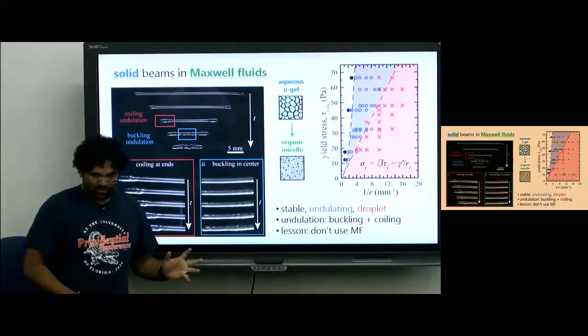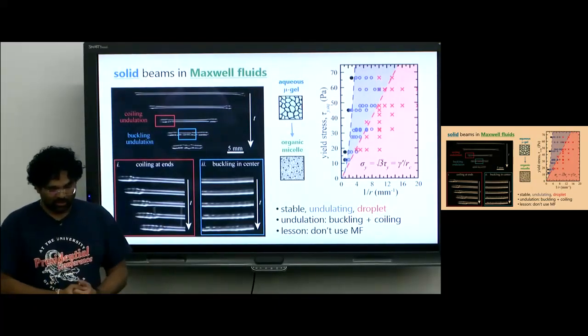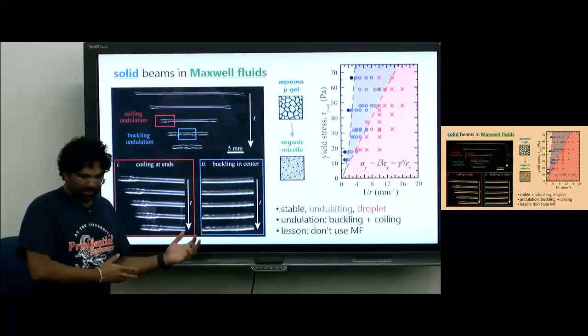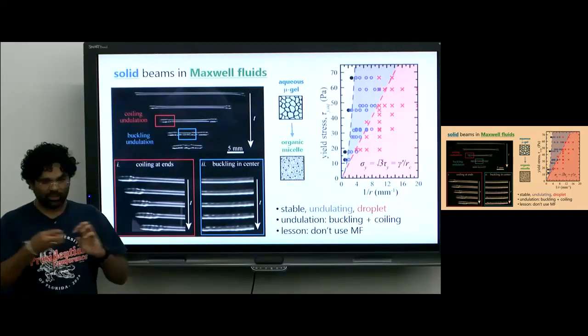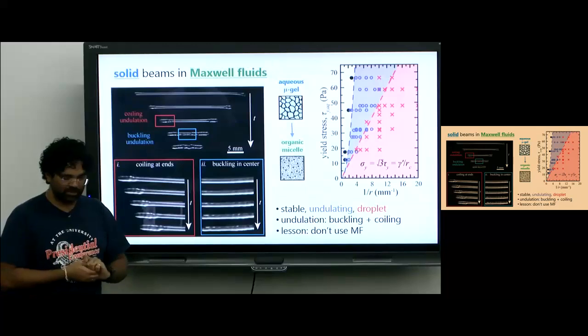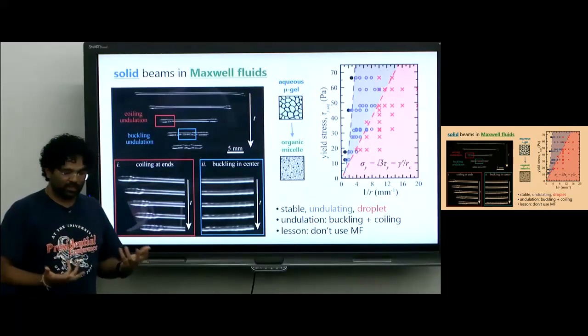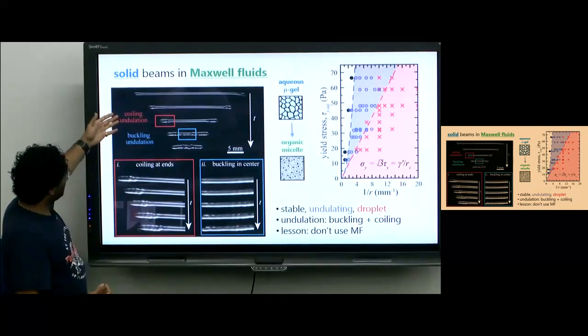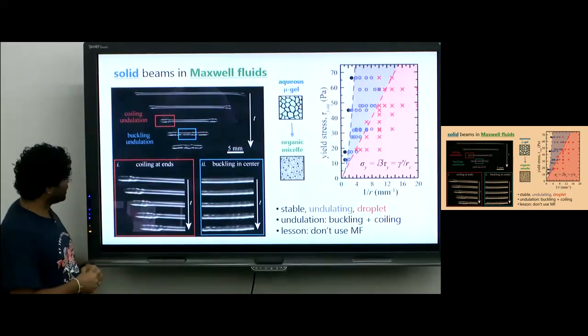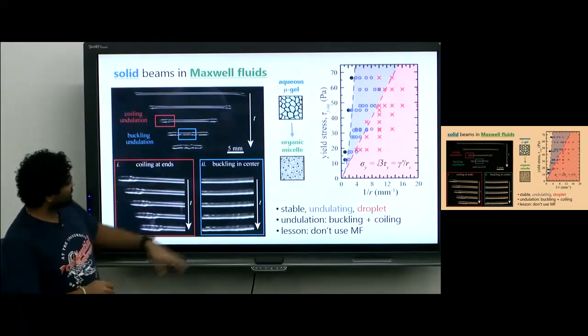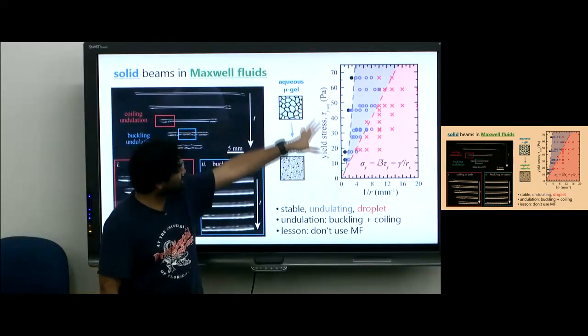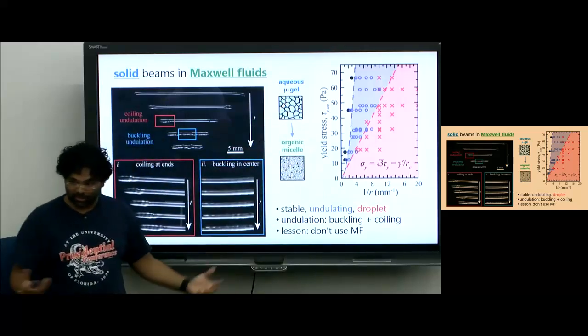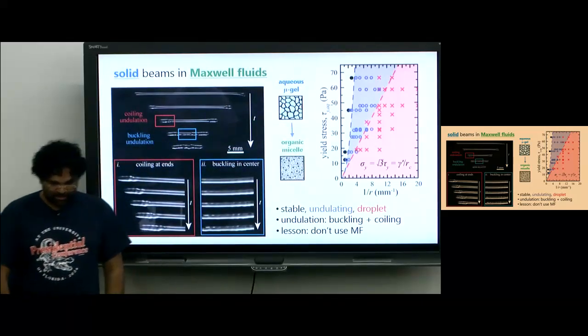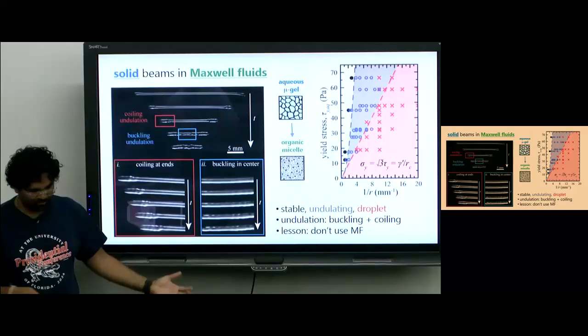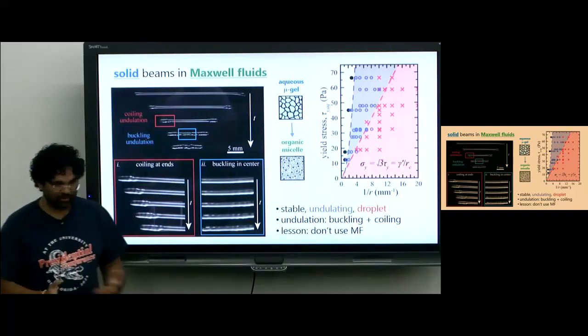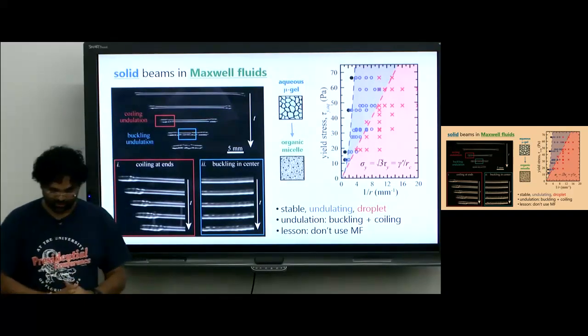And then there are these fluids called Maxwell fluids. If we try to print these solid-like soft gels into these Maxwell fluids, there are other problems that start creeping up, like coiling of the ends and undulations of the printed structures. And the stable window is really narrow. It's a really narrow window where you can get stable, good structures. So the general lesson here was to not go for Maxwell fluids when we try to do this sort of 3D printing.